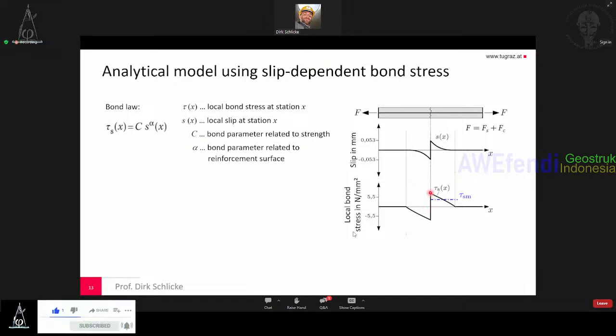We have bond stresses starting at the crack with the largest, and then it decreases, decreases, decreases until there's no slip, and then there's also no bond stress anymore. This is usually averaged with a mean bond stress, but that does not mean that this is a constant bond stress for all crack widths. This is only a mean bond stress over the slipping length.